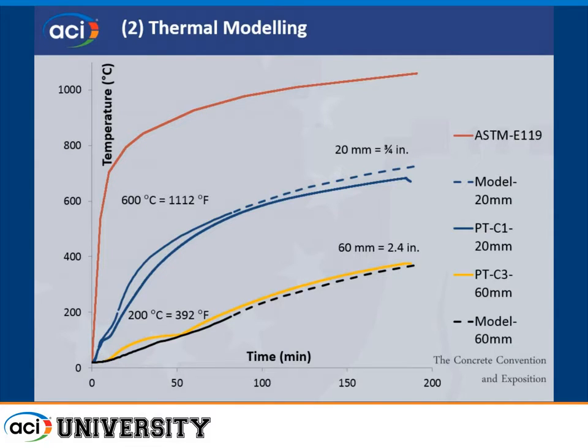This shows the furnace, the standard fire curve, and a numerical model shown by the dashes, at different depths through the slab. These are actually test results on FRP reinforced slabs. You can see that we can predict the temperatures with reasonable accuracy, so that doesn't seem to be too much of a problem. The caveat, as Luke mentioned as well, is what about spalling? We'll set that aside, so this assumes no spalling. We didn't get it in these tests.